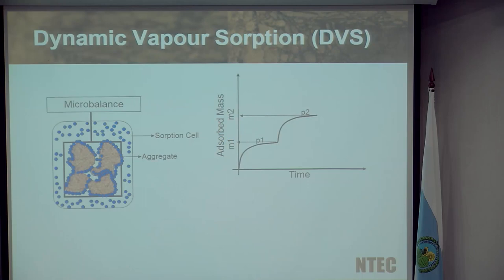Eventually, that will get to an equilibrium. Depending on how small the particles are, it could take a couple of hours. It could be done over a few minutes if it was a slightly larger particle. And then we would do, say, a third pressure. And you would keep on doing this till eventually you end up with what we call an isotherm. In other words, a relationship between the increase in mass of that aggregate particle as it gets covered with molecules of gas, as a function of the vapor pressure.